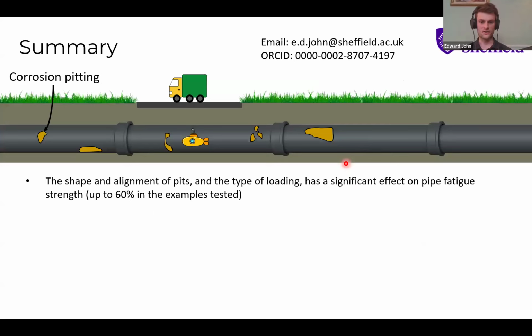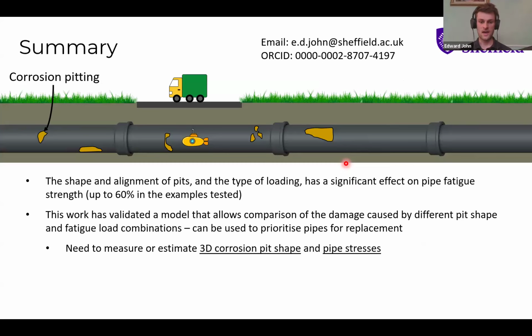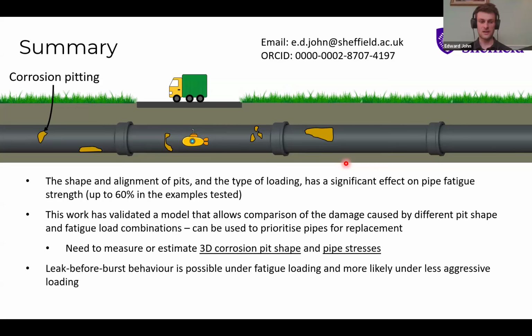So just to summarize, what we've shown here is that the shape and alignment of pits and the type of loading can have a significant effect on the fatigue strength of cast iron pipes, up to 60% in the examples we've tested. So we need to consider these factors when we're trying to assess the condition of cast iron pipes. And we've developed and tested out a model that we can use to predict this. And also we've shown that leak before burst behavior is possible under fatigue loading, and it's more likely to exist for longer under less aggressive loading. So yeah, that's all from me.